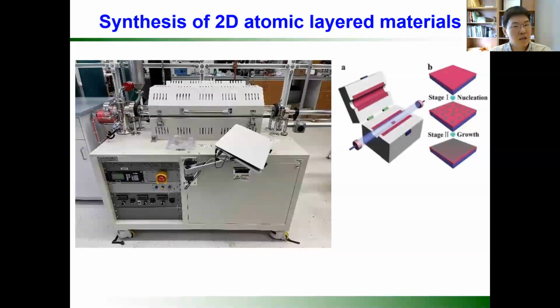So first, let's talk about how we synthesize those atomically thin materials. In our lab, we use a chemical vapor deposition tool. This is a tool we currently have in our lab to synthesize at large scale. You can think of a 5 by 5 centimeter scale. Using the catalytic film, we can synthesize those materials at a high temperature, like 1,000 degrees, using methane, hydrogen and argon. Those gases can be precursors.